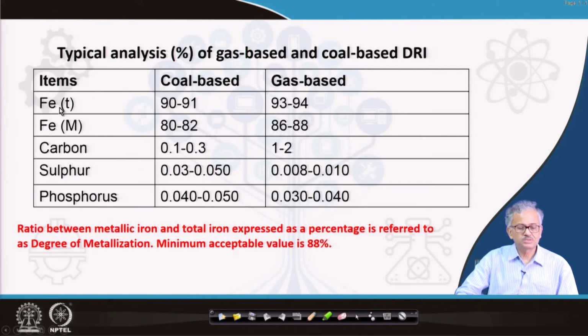And this is the typical analysis of the gas based and coal based process. You can see the metallic iron is higher in the gas based process, total iron is also high, and then metallic iron is high. The carbon is 1 to 2 compared to 0.1 to 0.3 in case of the coal based process. Sulfur you can see 0.02 to 0.05.